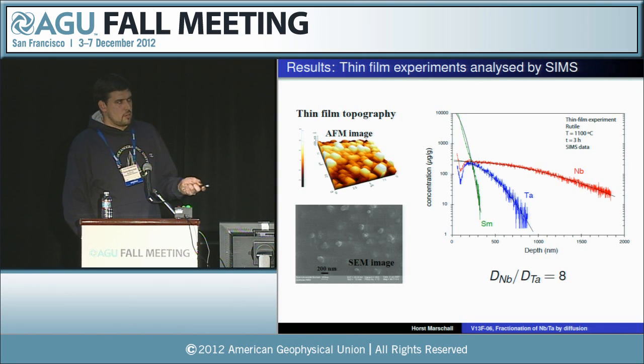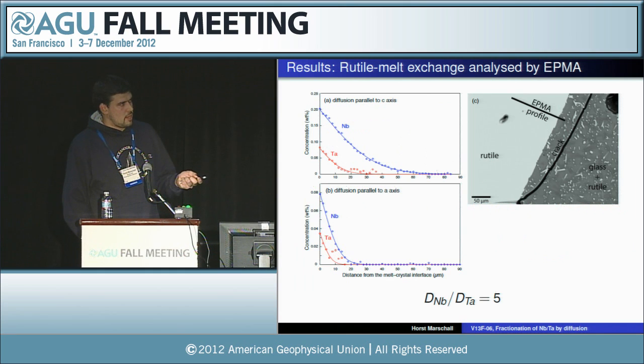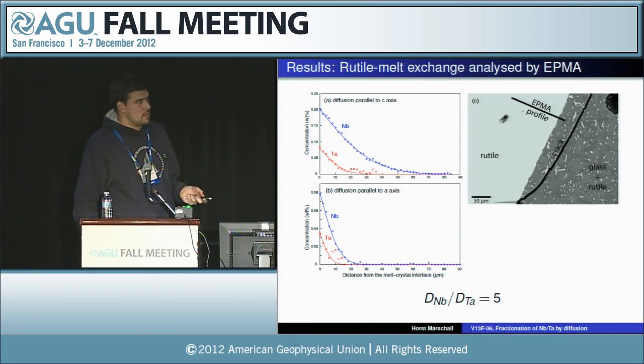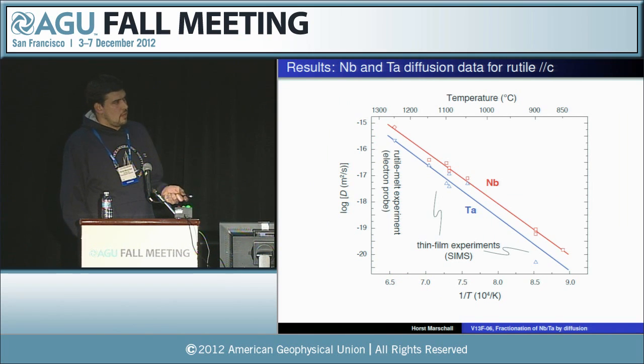So that opens the door to a very large kinetic fractionation of this element pair. In this particular case, niobium diffusivity is 8 times higher. This is the electron probe, so it's just sectioning the crystal and measuring profiles parallel to the C-axis in this case and parallel to the A-axis. So there's certain anisotropy of diffusion, but again, niobium is much faster than tantalum. And here's our collection of results between 850 degrees C and 1250, two entirely different analytical methods, and they correspond very well, and you have a good determination of the niobium diffusivity.